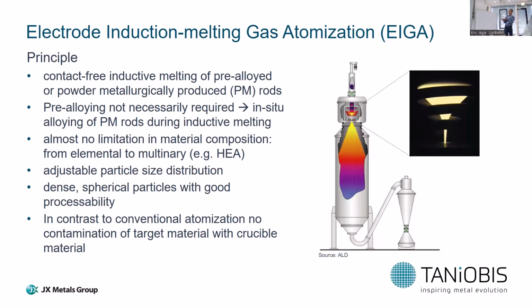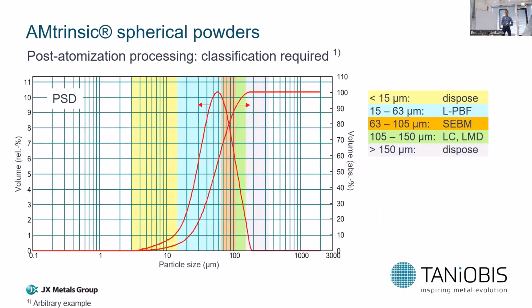This is usually a 90-degree tip, depending on the coil you are applying. Forming such a melt filament, this passes a nozzle, and thereby it is accelerated with argon gas and disrupted to form more droplets, which then solidify during the flight through the tower. The powders are then collected at the bottom or in a cyclone and further processed.